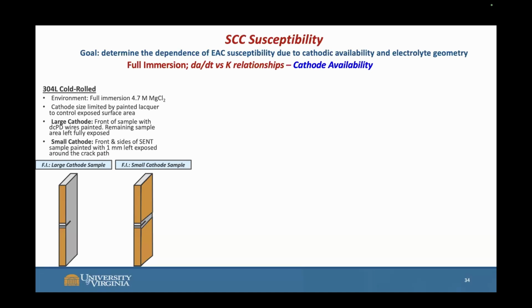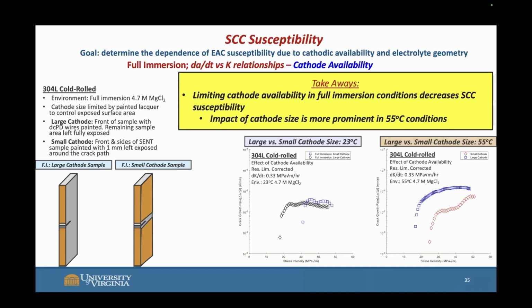One of them was a large cathode size where the DCPD wires were painted. And then the small one had 1 millimeter of free surface around that crack path. So we found that limiting that cathode size in full immersion conditions did decrease our SCC susceptibility, but one of the main things to take away is that this impact of the cathode size was a lot more prominent within our 55C testing conditions compared to the 23C in full immersion.